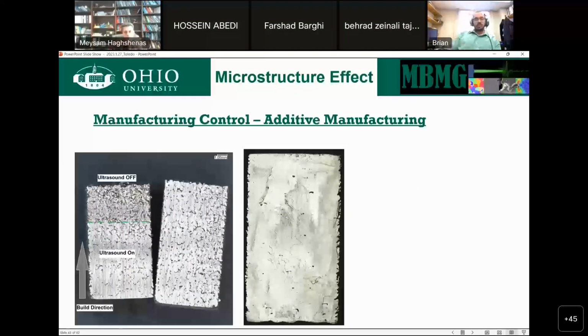So the concept is this. The left image here shows a case where we have ultrasound on and off. What effectively this means is, if you're familiar with 3D printing, particularly laser powder bed fusion, you have your build plate, you have your sub build plate, and then your apparatus that pulls that down as you build this thing layer by layer. What we're doing is we're sandwiching an ultrasonic transducer. So you can think of those physical sensors I told you we use for acoustic emission, the same thing can actually send energy. So if you put one of those between the build plate and the sub build plate and send energy up through the build plate, you can affect things like the porosity in the material.